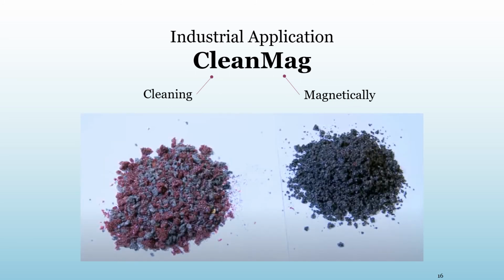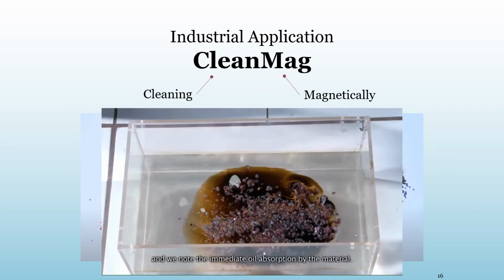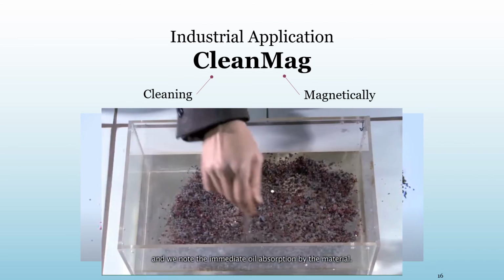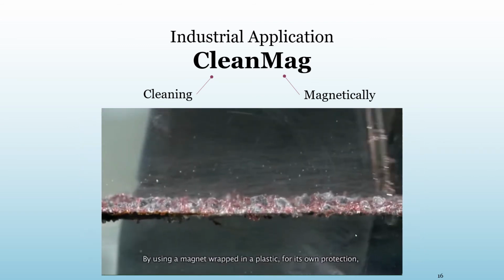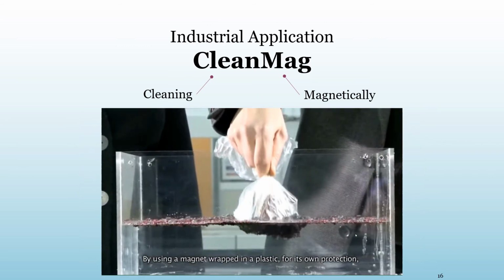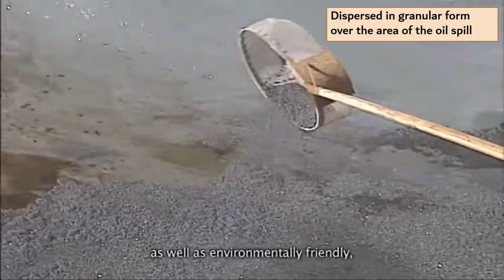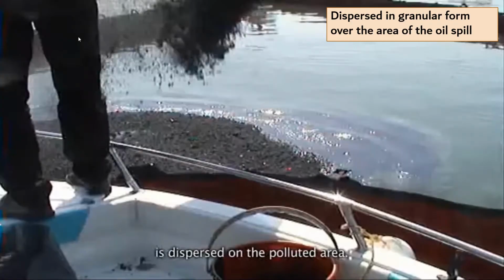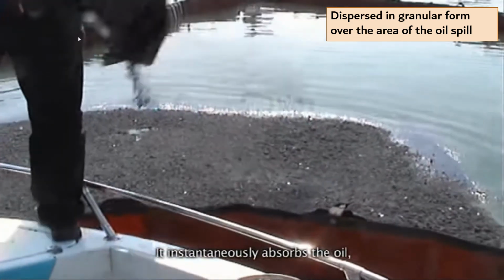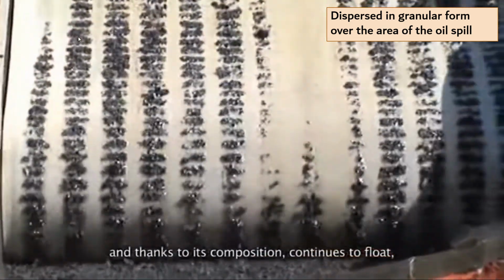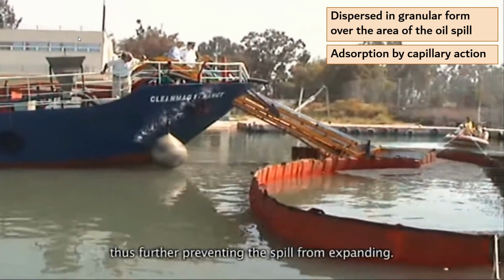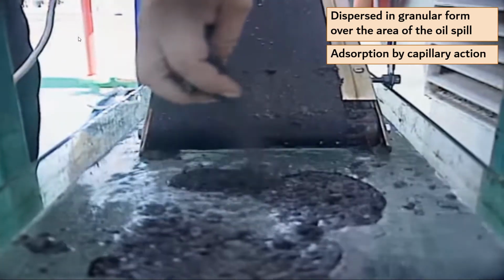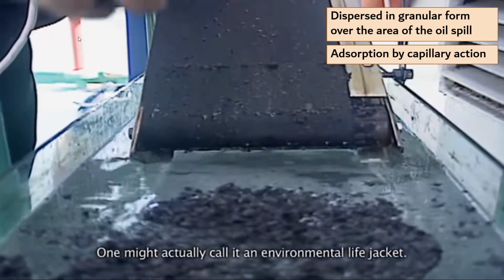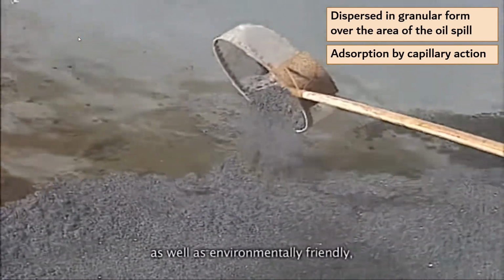CleanMag is a developed and patented oleophilic, porous, magnetic and oil-absorbing material. It absorbs only oil and no water. It has been tested and demonstrated on a large scale and in real conditions and has performed successfully. The CleanMag is dispersed in granular form over the area of the oil spill on the seawater. The spilled oil is instantaneously absorbed into the material pores by capillary action. It is unsinkable even under harsh weather conditions, limiting the oil spill expansion through emulsification.